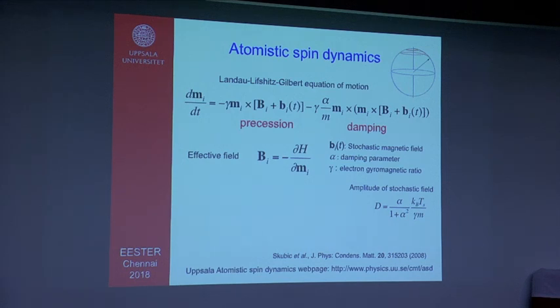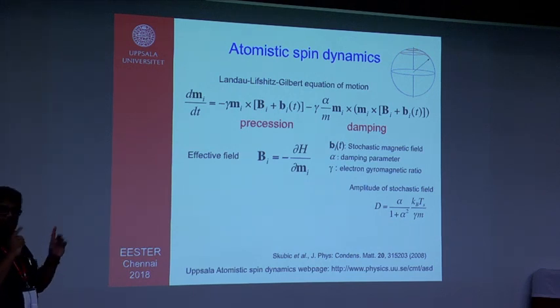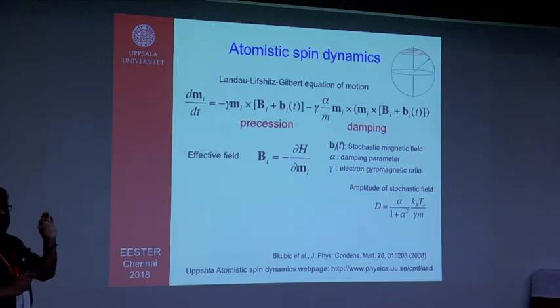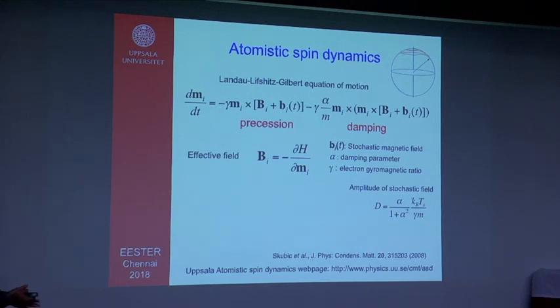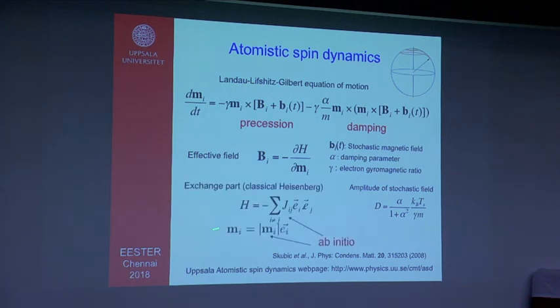Now, this is usually done in micromagnetic simulations, where a similar thing is done, but they do not consider the atomistic approach. They do not have the atoms or the atomic moments. They have a chunk of macro moment, and they work with that. The difference is that we have the atomistic approach. That means every atomic moment is considered here. So now this Hamiltonian we have. The final thing is how you define your Hamiltonian. Your Hamiltonian can be very large with all sorts of different terms. Here we mostly use the classical Heisenberg Hamiltonian, and both the exchange parameters and magnetic moments are calculated from ab initio DFT techniques, and we put them there. Then you generate the effective field and let the atomic moments evolve within this effective field.